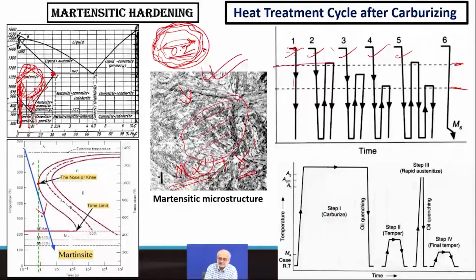That's not our target. So I would rather go for one of these treatments where, for example, I first heat the entire block, and then cool in air, so that I do this kind of a normalizing treatment. So I create a grain refined core, and then I do another heating, not above AC3 but just above AC1, and then quench. This is for the case or the surface, because the surface doesn't need this higher temperature. Even just above AC1 is sufficient, and when I heat above AC1, I'm already in the austenitic region, and now when I quench fast like this, I can convert that austenite to martensite. So 3, 4, 5 is a good enough cycle, a combination of cycles for converting the surface to martensite and also ensuring a normalized or fine-grained structure of the core.